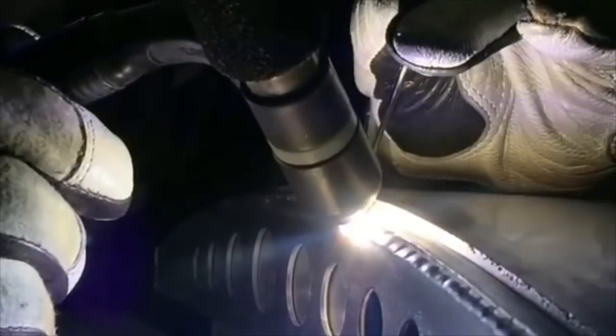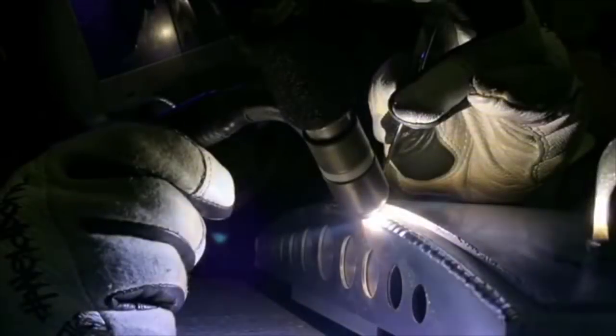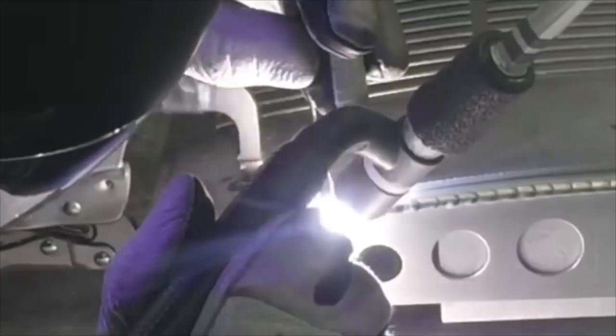Yeah, and talking about wire again, what size filler wire do you use for those outside corner joints on those, they look like shroud covers of some kind? Typically I stick with 1/16th. I'm right there with you. Most of those are 1/16th inch. Typically, whatever my metal thickness is, the closest rod size that matches that material thickness is usually a really easy, straightforward way to go.